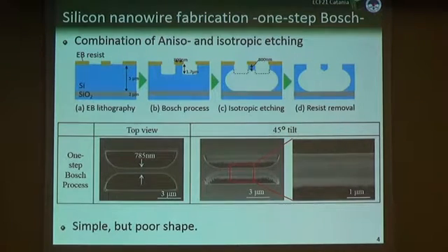Then these are the resulting nanowires. The width is good, but the thickness is larger. But this is not the actual thickness, as it has a remaining passivation film on the side. So the actual thickness is like this, which is around 800 nanometers. This is a very simple process, but the shape or the roughness is very bad.